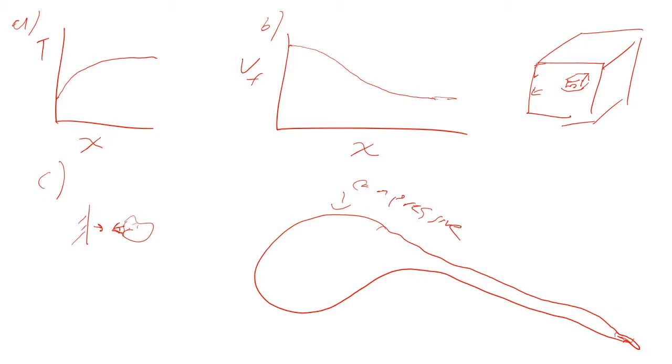Which way is it going to run? It's going to propagate lengthwise into this region where we've got huge compressives, right? So you're throwing the crack downhill in the worst possible way, right?